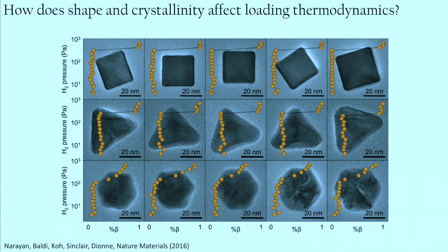So as our first set of measurements, we just kept everything in the dark and we want to know what's happening in thermodynamic equilibrium. So what we did is we set the hydrogen pressure to a certain value and then we used a combination of diffraction and EELS, they both give commensurate results, to figure out what phase the nanoparticle is in. And here I'm just showing you examples of five individual single crystalline nanocubes, five individual single crystalline nanoprisms, and then polycrystalline, or multiply twinned icosahedral nanoparticles.